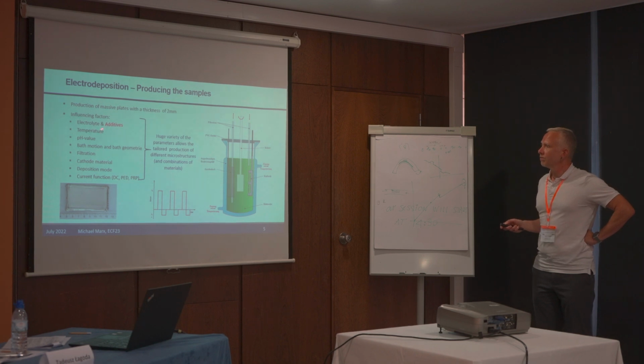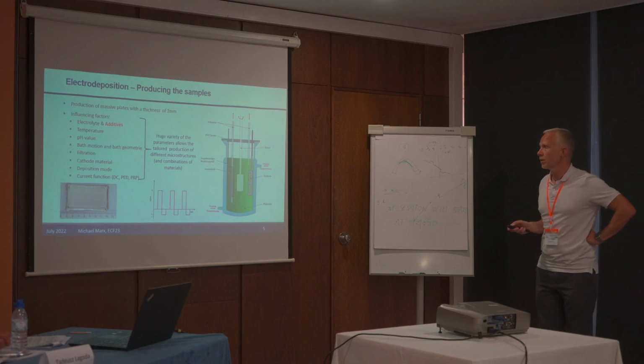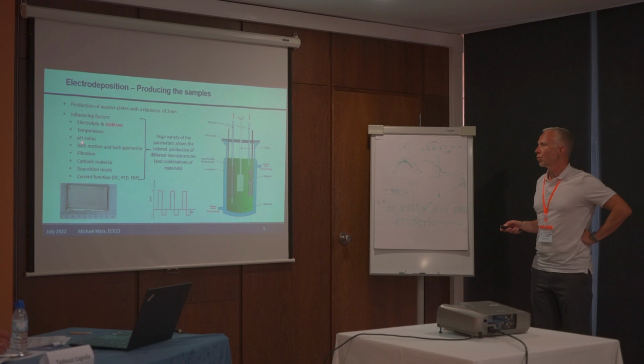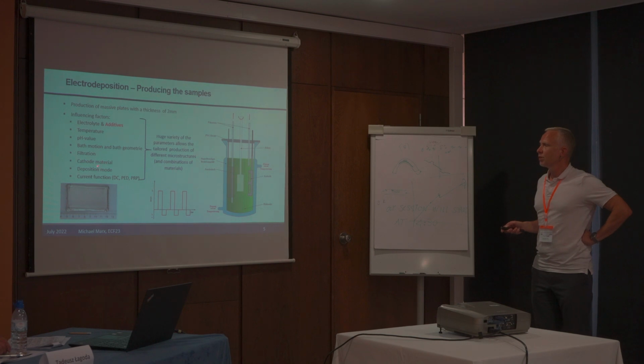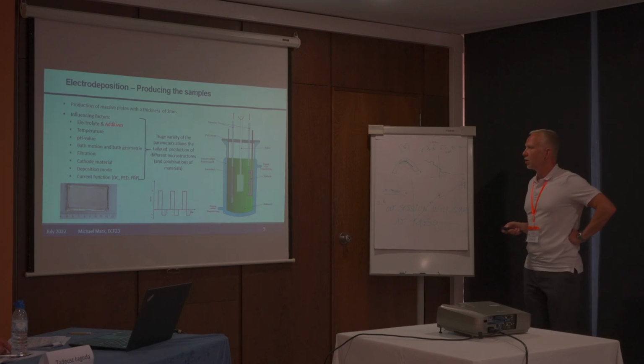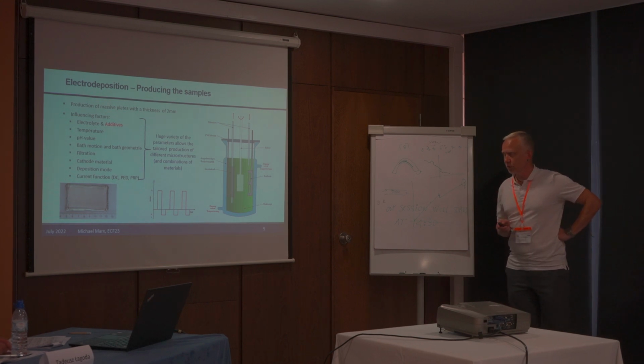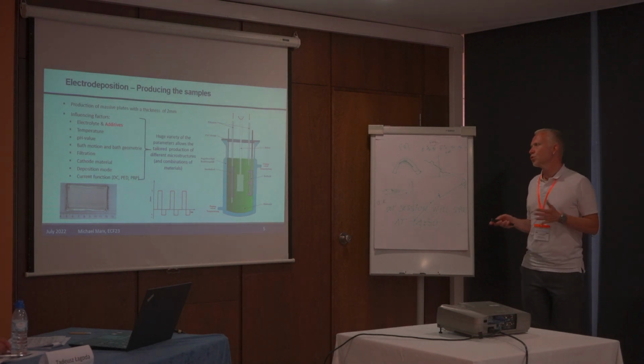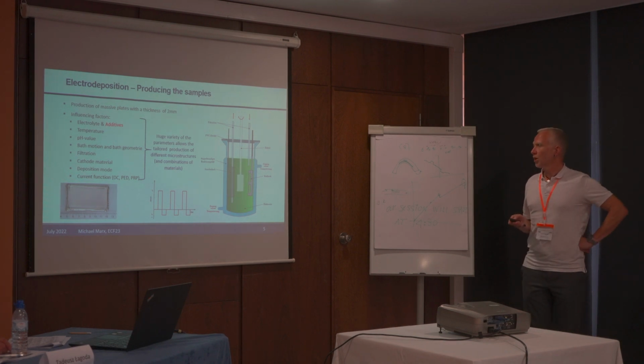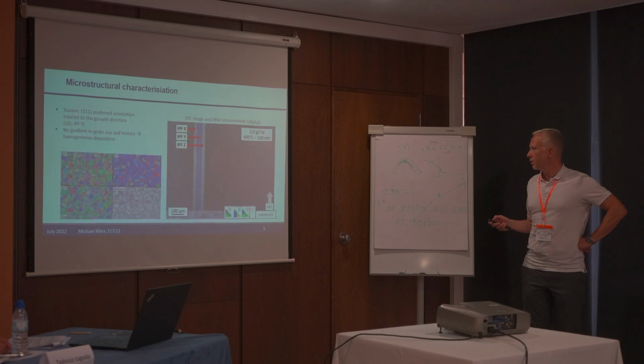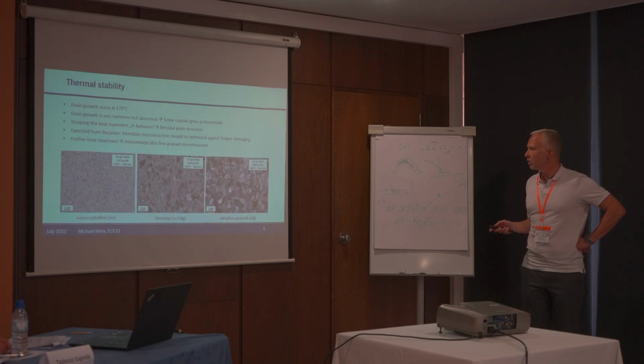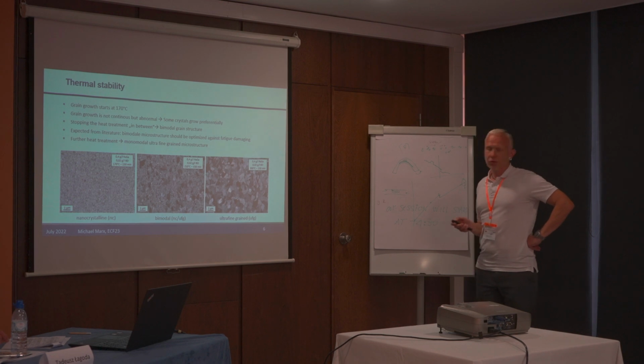And we have a lot of influencing factors: our electrolyte, the additives, which is very important in our case, the temperature, pH value, the motion of the bath and the geometry of the bath, filtration, cathode material, deposition mode, and the current function, if you have direct current or pulsed current or reverse pulses, as you can see here. This is a huge variety of parameters, and we can use it also to tailor our specimen, our materials and microstructure.